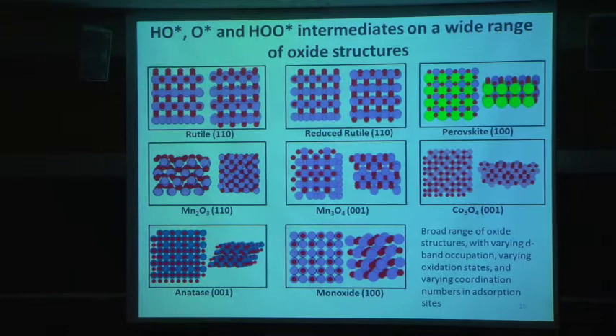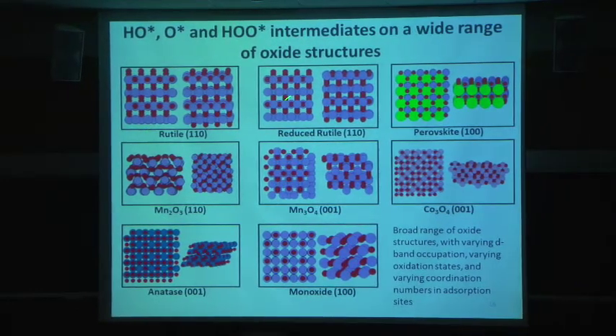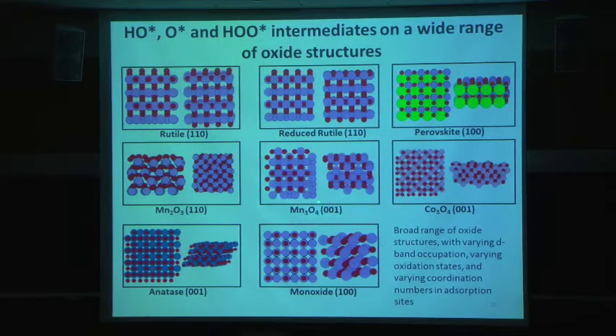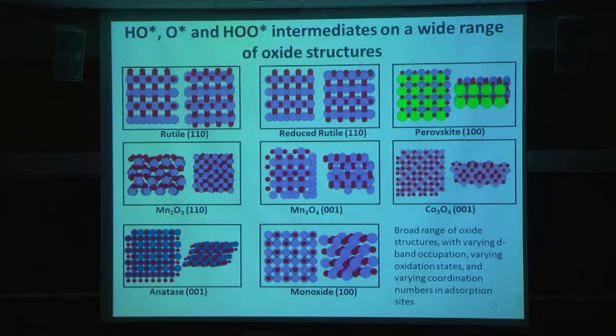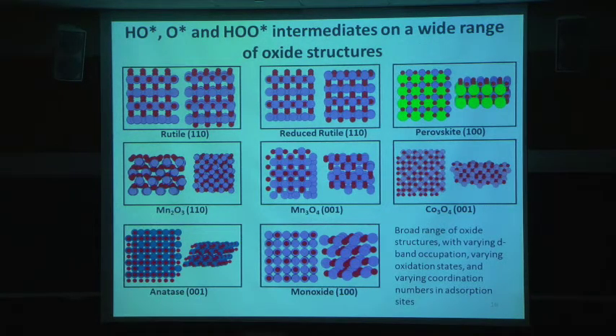We know of lots of metal oxide structures: rutiles, reduced forms of it, perovskites, cobalts, manganese oxides, anatase, rock salt structures. All of these kinds of oxides exist. And since we're working in a computer, we can generate these structures, and then we can populate them with all kinds of different metal sites. So we can look at different metal oxides. Some of them may not even exist, but for understanding whether our descriptors are correct and the physics are correct, we can calculate the energy of each one of those steps on each one of these kinds of surfaces and try to find out, does something exist that would be perfect?